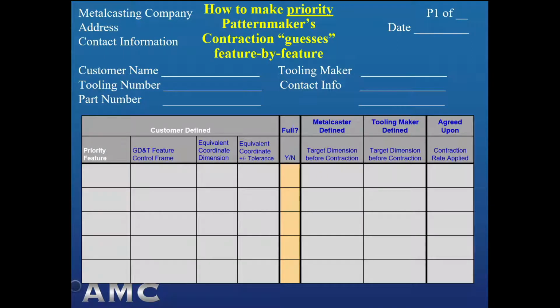Listed in the rows are all the features of the casting design that I was worried about. They were either critical or significant features with tight dimensional tolerances, or they would be formed in the mold in a way that I thought could cause contraction rate problems. I would take my chart to the mold cavity tooling builder, and we would collaboratively decide what rate to apply on each feature that was listed. If we missed, we missed. We would have to fix the tooling and make new prototype castings to see if we did fix it, but we tried, and at least we thought about it carefully.